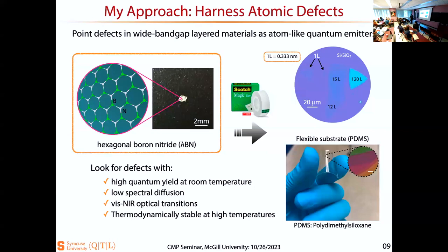Another reason for me not working with the CVD grown sample is that the photophysical properties of the color centers are much better in the single crystalline than in the CVD grown sample. And the second reason is that the thicker the flakes are, the more stable the quantum emitters are. So let's say the flake is 300 nanometers, then you have uncertainty anyway. Is it at the lower edge? Is it at the upper edge? If it's in the middle, your uncertainty becomes larger and larger. Yeah. So does that answer?